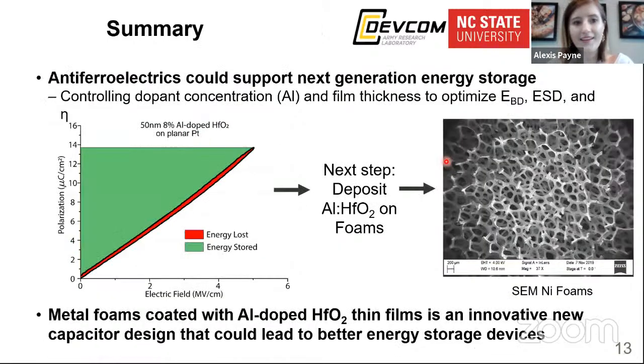So in summary, antiferroelectrics could support next generation energy storage devices. And by controlling our doping concentration and film thickness, we can optimize for the properties that matter at the operating voltage. And as much as we've deposited aluminum doped hafnia on foams, our next step is hopefully to measure successfully an antiferroelectric loop from the hafnia thin films deposited on the foams. We still believe that metal foams are going to be an innovative new capacitor design that could lead to better energy storage devices.